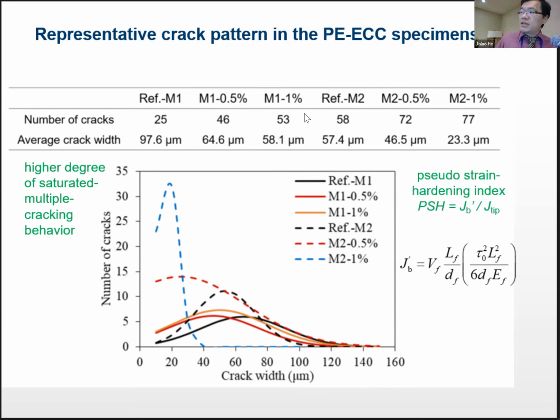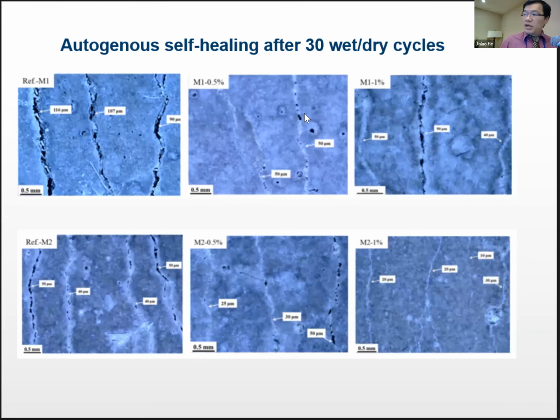Again, if we consider the hardening index, which is the J_b prime divided by J tip, that means not only did we improve the fracture toughness, the J tip, but also we further improved the other one, the J_b prime, because that's the amount of complementary energy you need to induce additional cracking after the first crack is formed. So it's all going in the right direction. And we did see this kind of behavior. Again, the high volume fly ash one gives you much better self-healing.